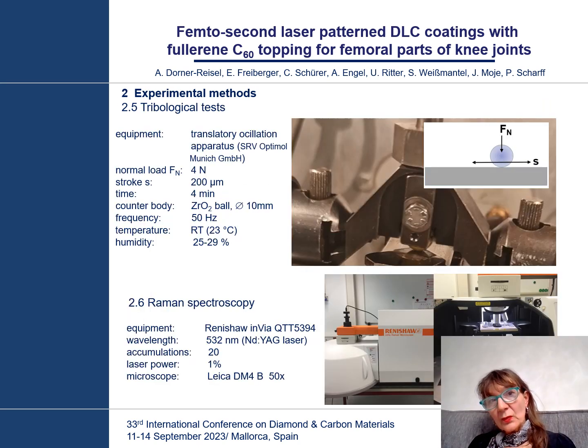Tribological tests were done with a ball disc apparatus. A zirconia ball did slide along the sample surface with 50 Hz, a normal load of 4 Newton, and a stroke of 200 microns. On selected positions, also Raman spectroscopy was done with a green laser.